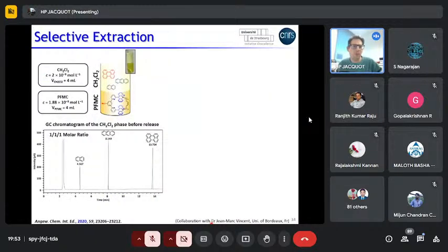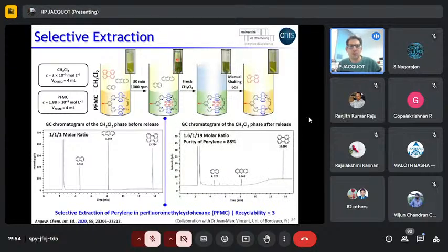And then we went a little bit further. We looked at a 1-to-1-to-1 mixture of perylene, anthracene, and naphthalene. So they were in the DCM source phase, and you have the GC chromatogram of this DCM source phase, and you do see 3 peaks. After stirring, we have a color change. So we have a host-guest complex which is formed, and upon changing DCM by fresh DCM, we can release the guest into the DCM receiving phase, and you have only 1 peak in the GC chromatogram for this phase, which is the peak of perylene. So in other words, we were able to selectively extract perylene out of a complex mixture of polyaromatics. And if you want to do it by column chromatography, you will always end up with a complex mixture of polyaromatics. So that's pretty efficient in our case.